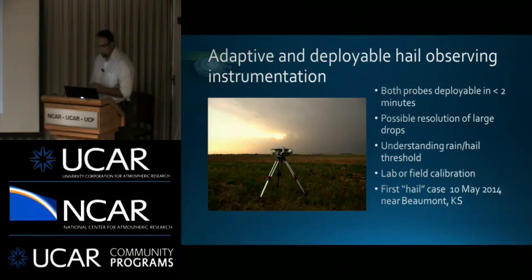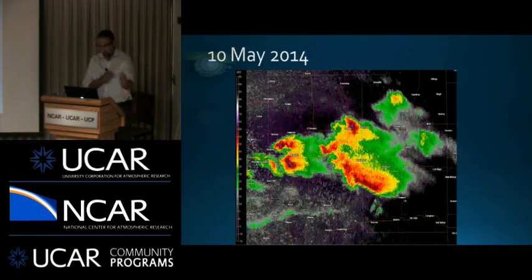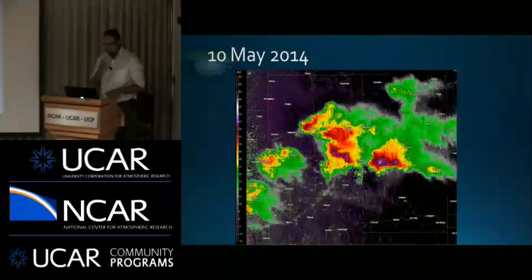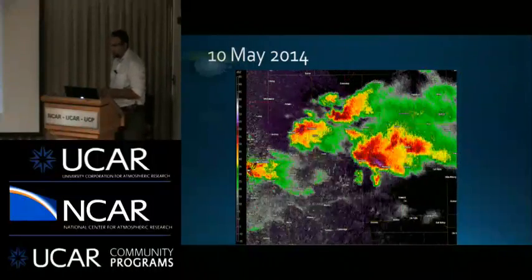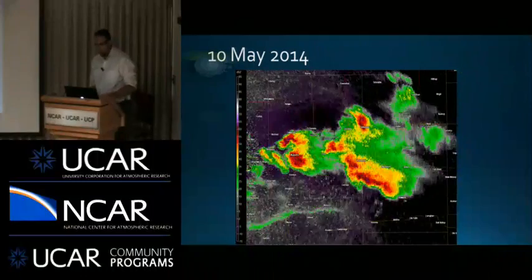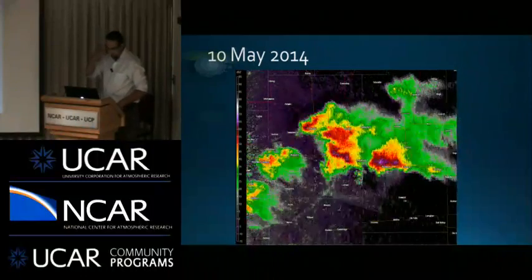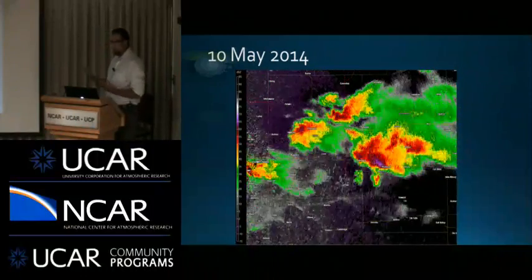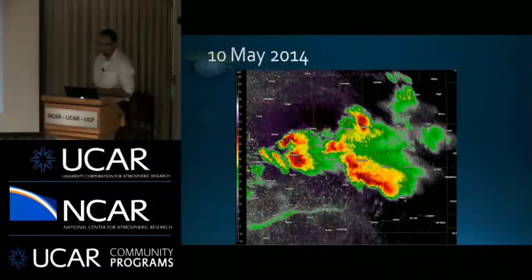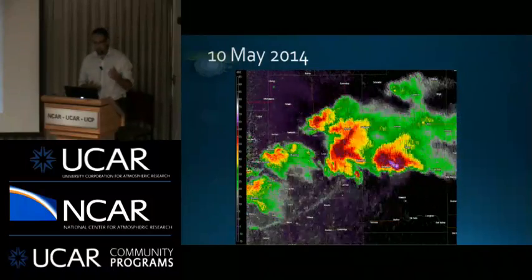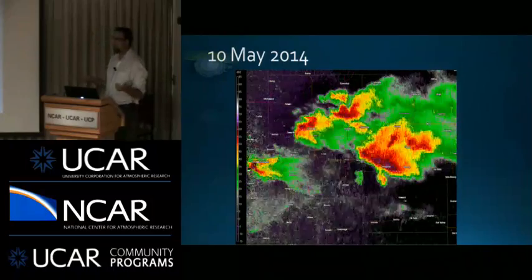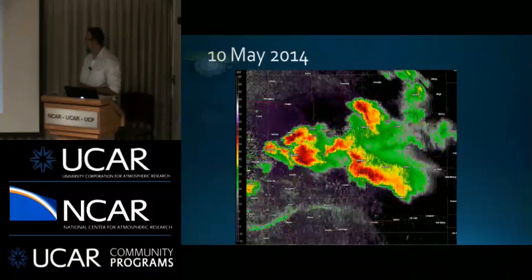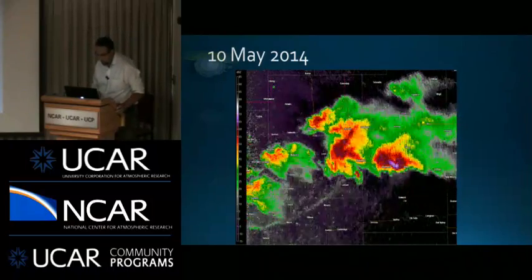So the first real case was 2 weeks ago. I guess it's 2 weeks ago, might have been less than that, near Beaumont, Kansas. And here's what it actually looked like. There was one cell that passed over the probe, and then we looked up and got the hook portion of a supercell. I kind of joked that this was a better-lucky-than-good kind of deployment, where you're targeting that initial cell that essentially gusted out a little bit. And then we lucked up and got another supercell that passed over the probe after that.